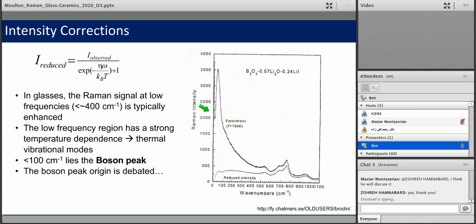So to get rid of this enhancement due to the vibrations not being in the ground state to start with, you can divide your observed intensity by the Boltzmann distribution given here, and you see that the temperature is on the bottom, so you'll end up reducing it, and you'll get a spectrum like this. There's many other intensity corrections out there, for instance, the long correction.